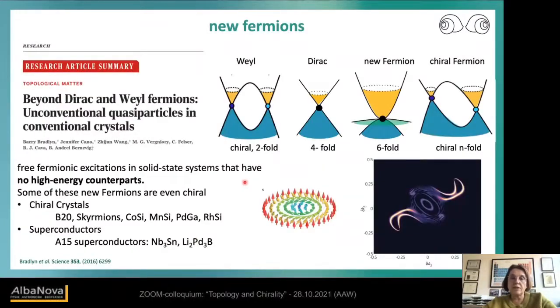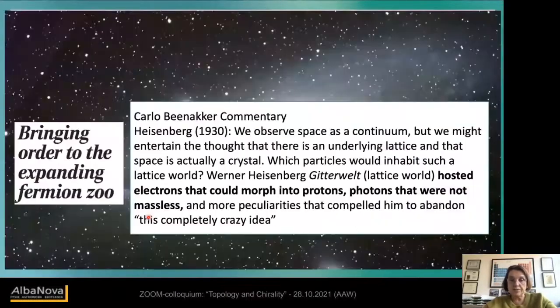So despite having chiral electrons, we can combine chirality in the crystal structure and chiral fermions. And this was done, the prediction in this paper. You can go maybe beyond the 4-fold degeneration by going to 6-fold degeneration or 8-fold degeneration. But in a chiral crystal, we can also have these degenerate points of Weyl fermions at different energies. And in this article, we already predicted a series of materials, and the B20 compounds are especially interesting because they are crystallographically chiral. And this has led to a nice conclusion from the referees of our paper, which I like.